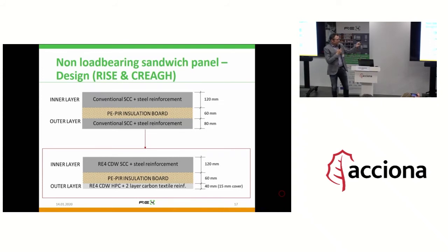By this we can reduce the thickness of the outer layer by half. And this and the fact that we don't have steel reinforcement in the outer layer reduces the weight of the entire panel by approximately 20%.